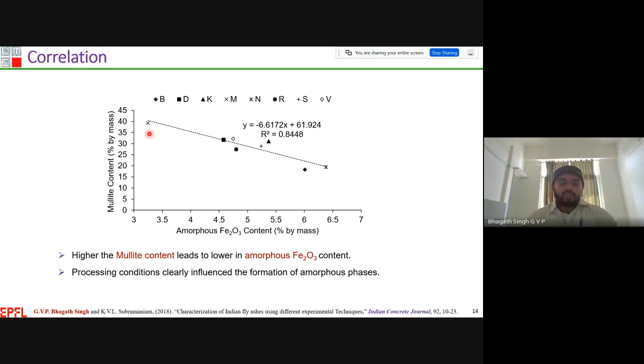If we have a higher formation of mullite phase, it will clearly reduce the amorphous formation in our fly ashes, because we have to take proper precautions in the electrostatic precipitator while we are doing the processing.